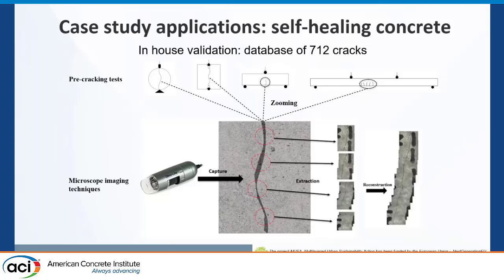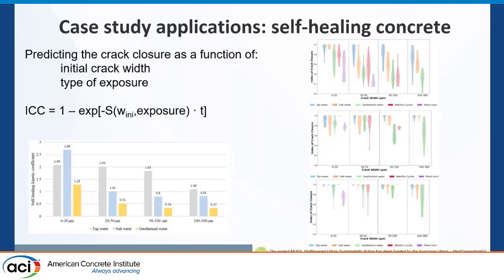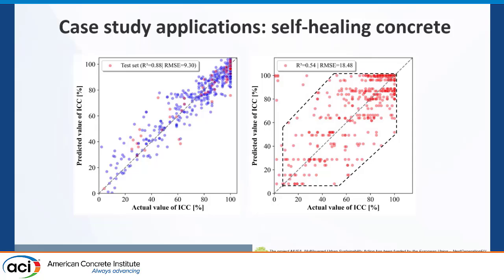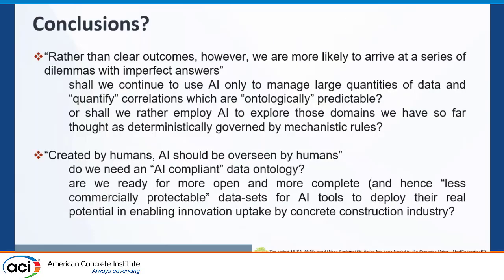So we ended up with information about more than 700 cracks. We monitored all those cracks for up to 1 year. So we have about 3,000 images that constitute our database. We interpreted them with statistics, trying to calibrate a crack closure kinetic response. Then we used artificial intelligence, and in the end, we realized that if you use AI, what you get is a prediction which is much narrower than what you can get with statistics, because with statistics, you just end up with the best R-square. So summing up, conclusions.